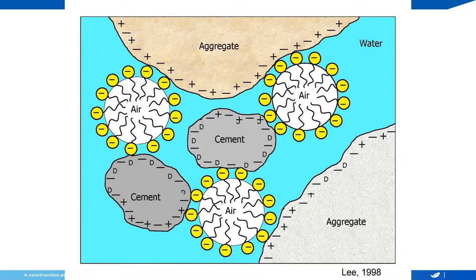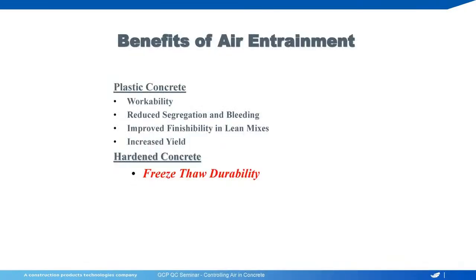Okay, so benefits of air, obviously workability is a side benefit of that. You can get less segregation and less bleeding with air because those channels are now disconnected because you've got the air bubbles in between, so that water's got to work harder to bleed out. You do get better finishability with low powder content mixes. If you have high powder content mixes, a lot of air can cause it to behave a little bit sticky. Of course, we get more yield out of the same batch of concrete when you have air in it. And then the main reason we use air is for freeze-thaw durability.